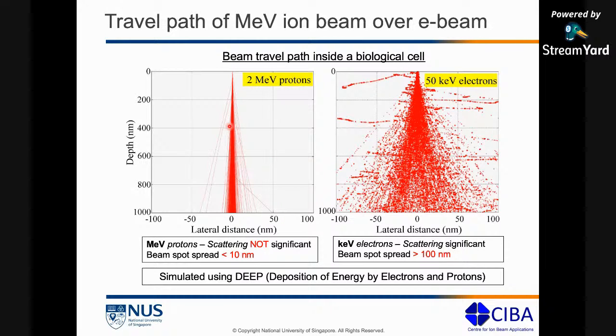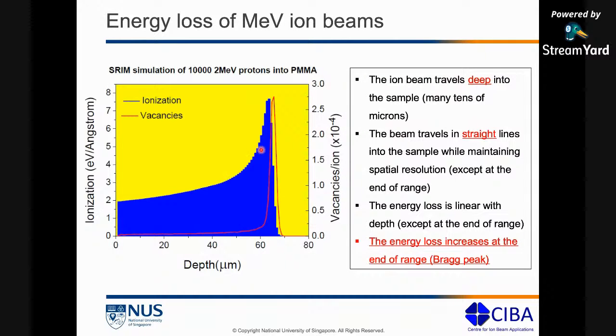Added to this streamline effect, if we go one step further and take a look at how the energy loss happens for 2 MeV protons into a material, this is what we get. This is a SRIM simulation of about 10,000 protons at 2 MeV into PMMA. As I said before, as they enter, the scattering is hardly significant, but as they start to slow down at the very end, they will deposit all of their energy and come to a complete stop. And that gives rise to this peak that we call a Bragg peak.